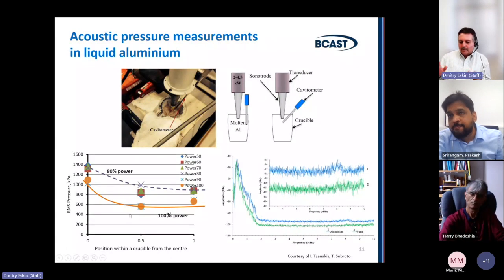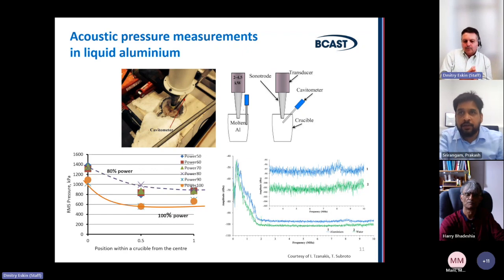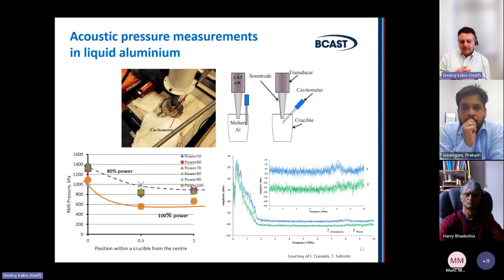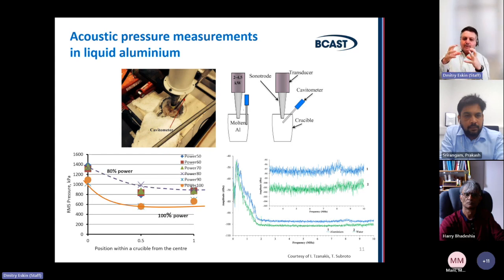Viscosity plays a very important role. There are two parameters of liquid metal which are very important for development of cavitation and acoustic flows: surface tension and viscosity. Density plays a role as well. But if you talk about alloys or materials of similar density range, then surface tension and viscosity. If you have a low surface tension, bubbles are created very large, they're very easy to form. And if you have high viscosity, the process is slowed down. Actually, in glycerin, for example, you can hardly see implosion of bubbles. They are created and they grow very slowly, and the flows are very slow. So everything happens like in very slow motion. Glycerin has very high viscosity.